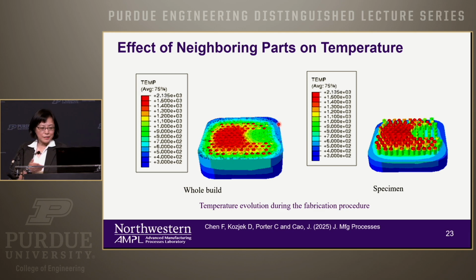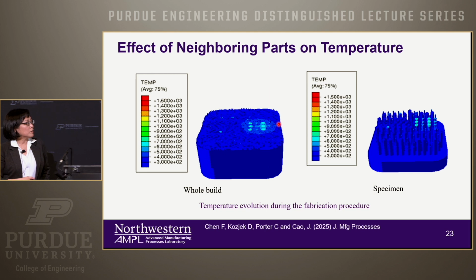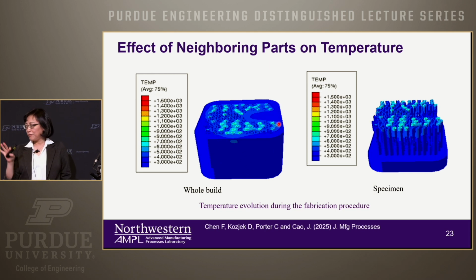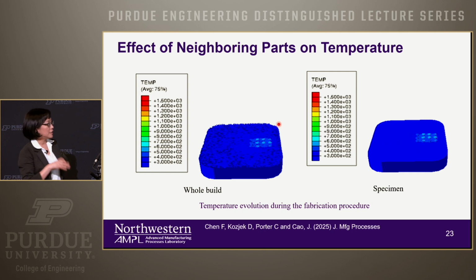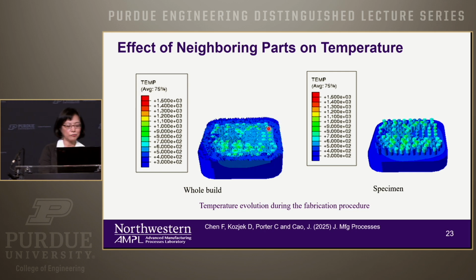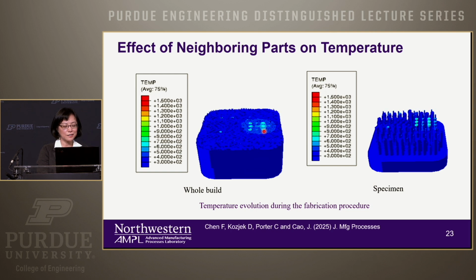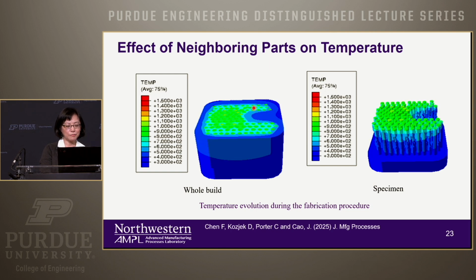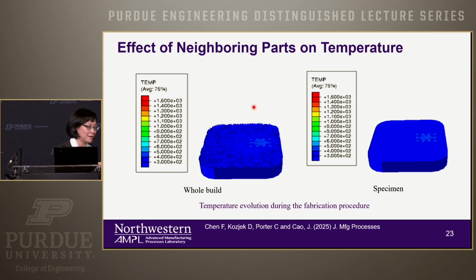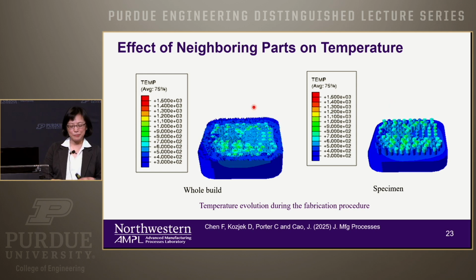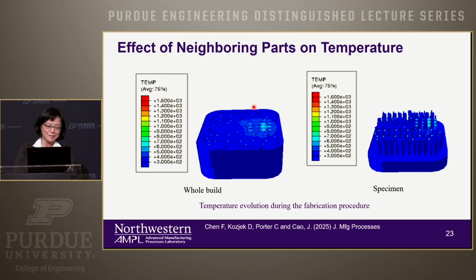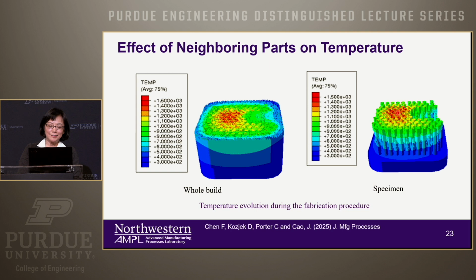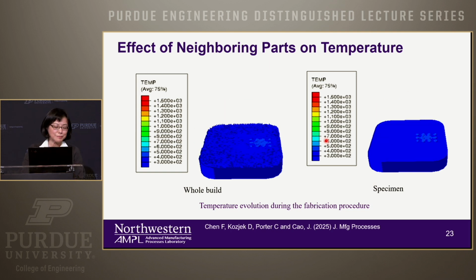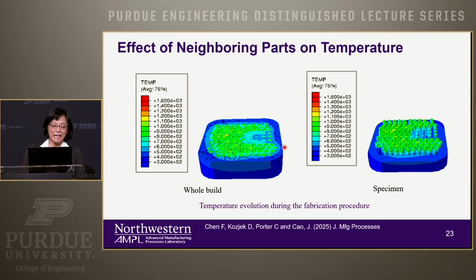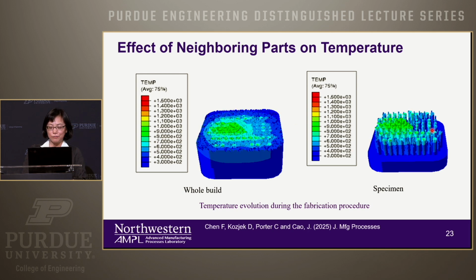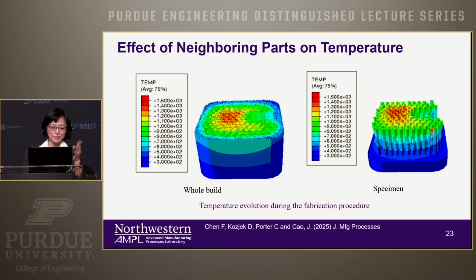The particular work that we are doing here is we want to check the effect of the neighborhood parts. For example, if we are just interested in these regions, because when you try to build AM parts, you try to stack as many parts in there as possible, right? Because the build time is pretty much dominated by the number of layers. So people put lots of tensile specimens and other things. Our question is how the surrounding areas will affect the parts, depending on where you are.